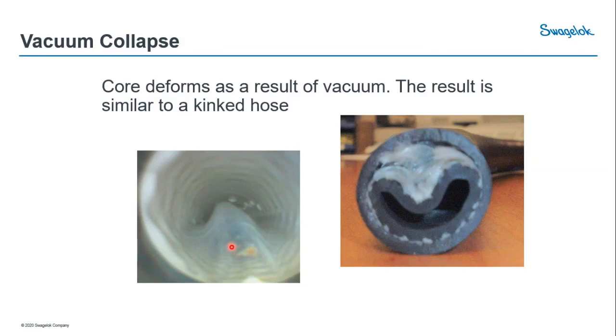Where we see this happen quite a bit is in steam applications. Steam will expand 1600 times, but it'll also collapse 1600 times. So if you have steam in a line, then you shut down the system and just let it go without draining out that hose, that hose will go from a vapor to a liquid, and it'll collapse 1600 times, and that'll pull that hose right in. We've seen that quite a bit in steam applications.